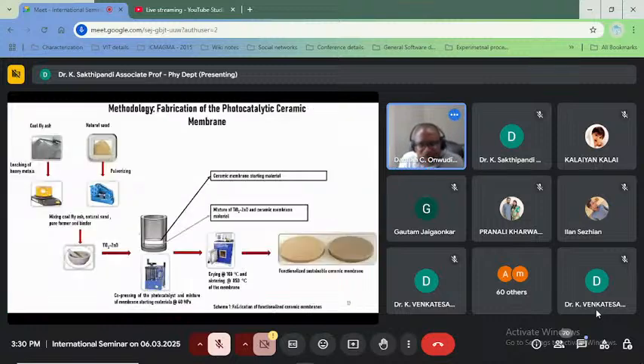Next slide is the construction process, the fabrication process of the ceramic membrane. First, the coal fly ash is leached. I'm on the left panel. It is leached through the addition of acid. First of all, before leaching, it is subjected to calcination at 1000 degrees Celsius to remove all the organic material. After removing all the organic material, it is then leached using acid to clean it up.